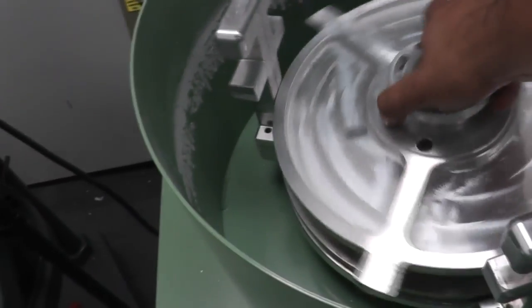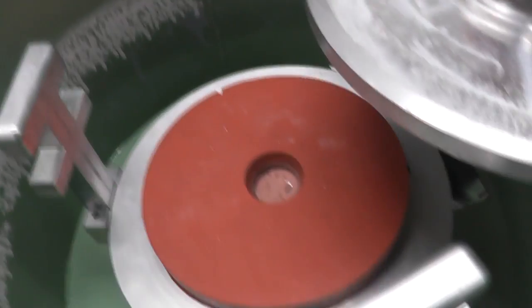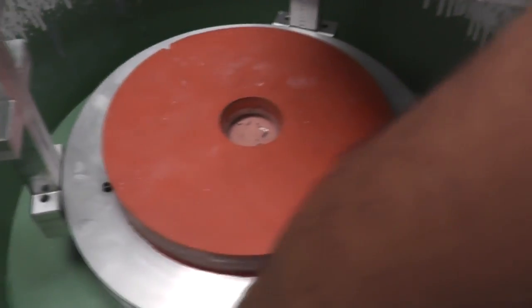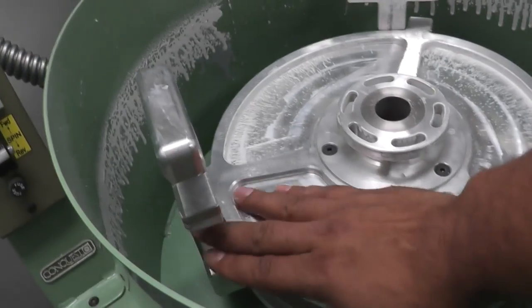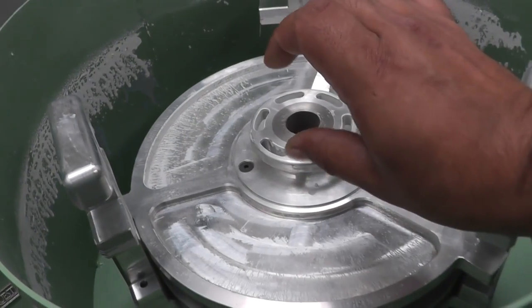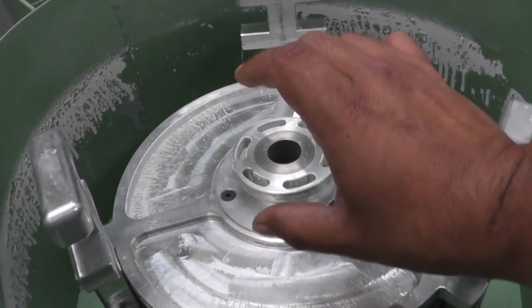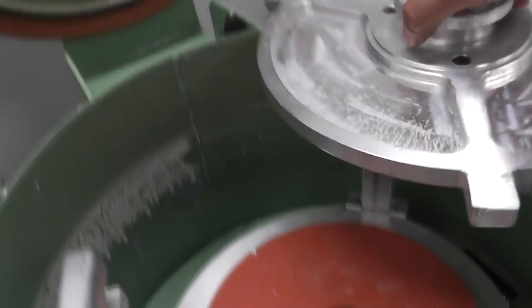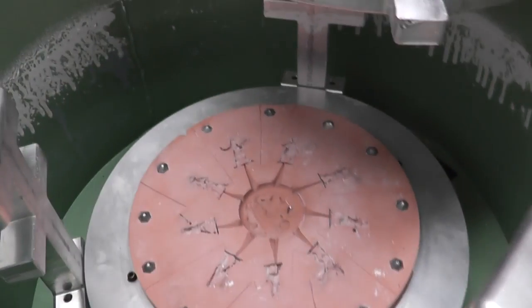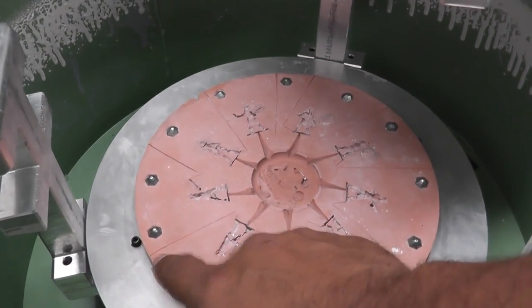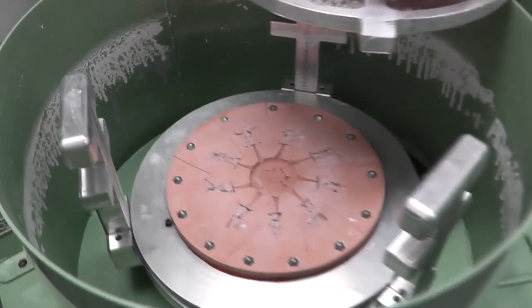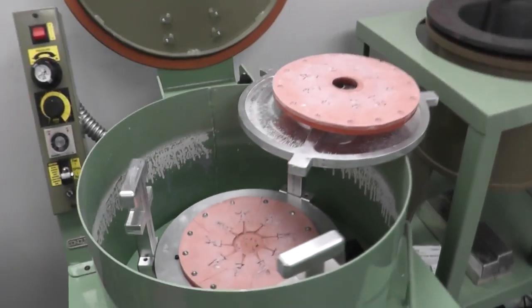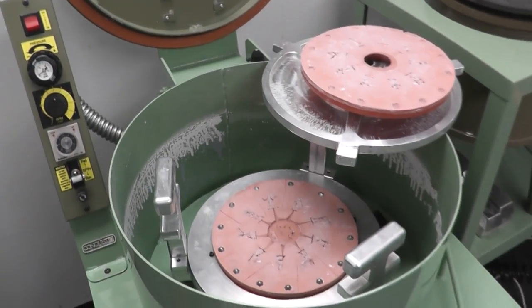The pressure dictates this plate in here. That bottom plate that the mold sits on lifts up and this locking plate locks in place and the pressure in between the mold is relevant in terms of these little gates and the vents and stuff and if the pressure is too much the vents get squashed and your figures get sort of squished, not correctly.